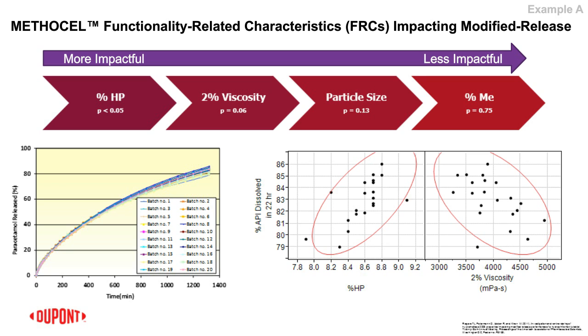And then we subjected them to dissolution testing, and you can see here on the left-hand side you have essentially 20 modified release profiles that are, for all intents and purposes, at first glance, right on top of each other. Okay, we did our best to minimize measurement variability. For those who have ever developed dissolution methodology with hydrophilic matrices, they can stick to the surface, they can float. So we basically minimized that measurement variability as much as possible using sinkers, using hanging baskets, these sorts of things. And these are the resulting 20 modified release profiles.